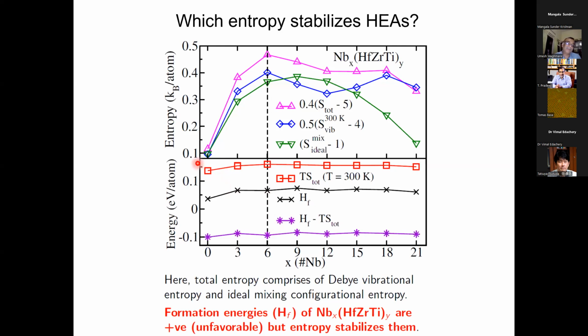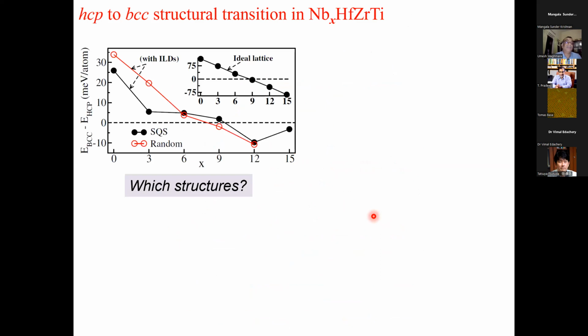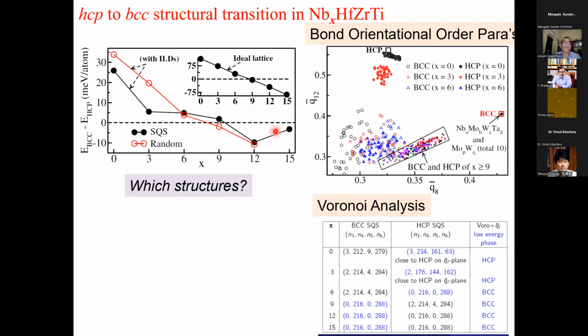This is the free energy, and you see the total energy is positive, which means these alloys are not energetically favored, but only if you include entropy, you get free energy stabilization of these interesting random systems. Then we looked at composition-dependent phase transition. If you increase the concentration of niobium in this high entropy alloy, we reproduce the HCP to BCC phase transition, and the characterization was quite tricky.